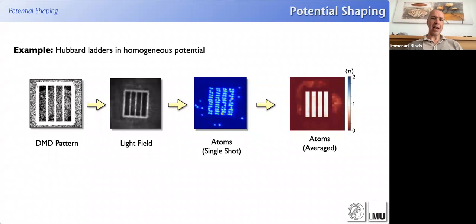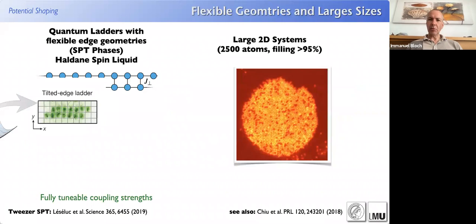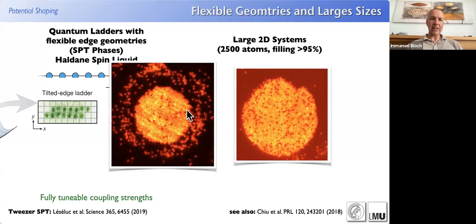Okay, these techniques we now use to actually realize much larger systems also. So some of the records we've been able to achieve in the lab, our system size is about 2,500 atoms, so really very, very large atom systems, as you can see here. Here they cooled a bit more, where we basically now have a very homogeneous region of about 1,500 atoms and a few hotter atoms at the outside boundary, with the cold atoms remaining here in the center of the system. So these are pretty much the sizes of the systems we can look at today with these atoms.